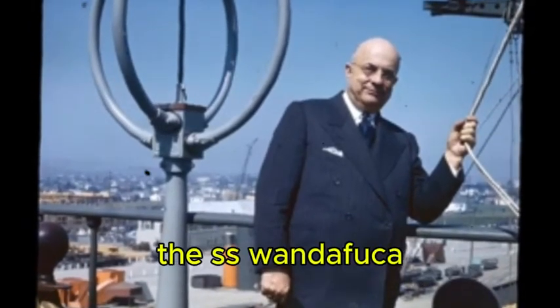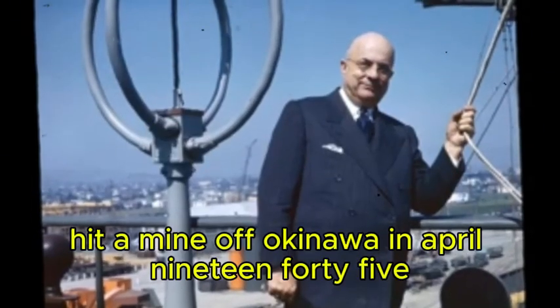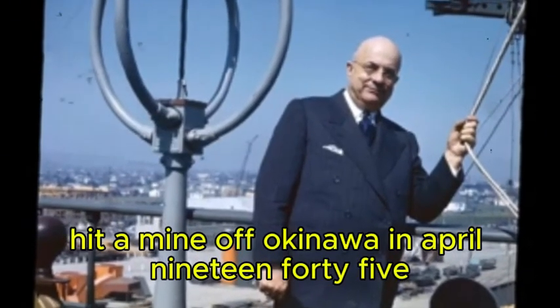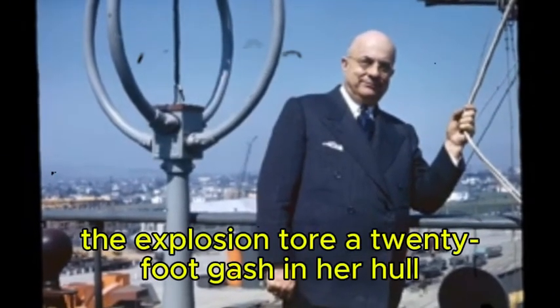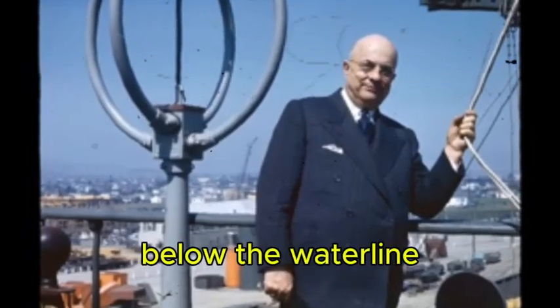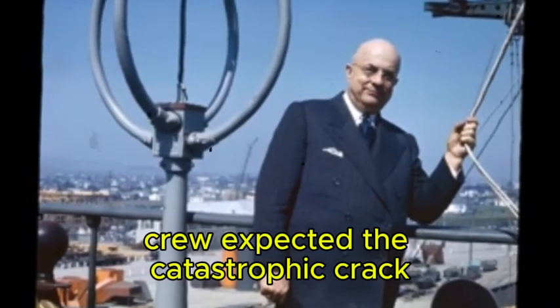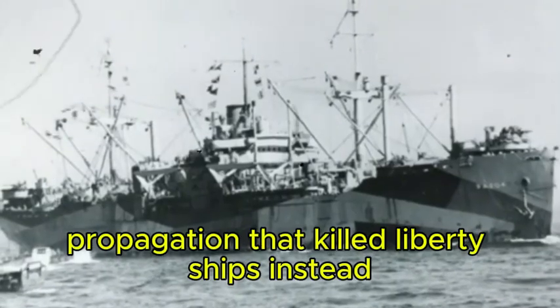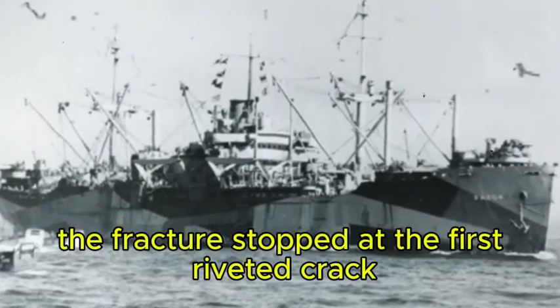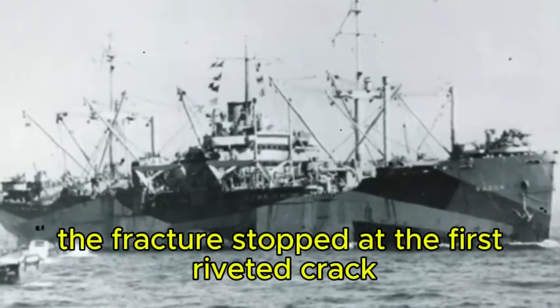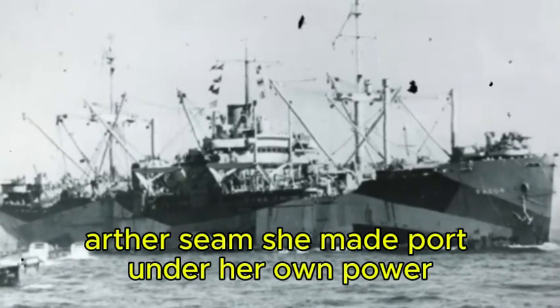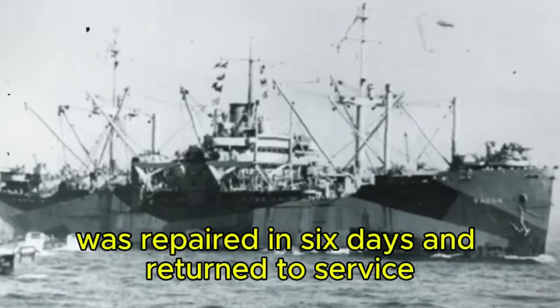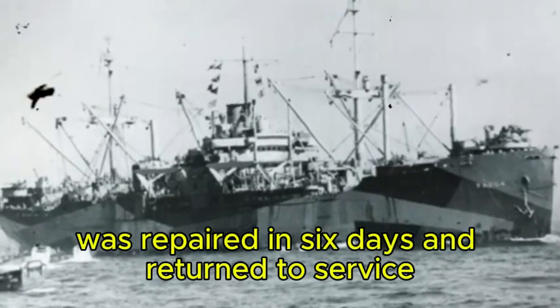The SS Juan de Fuca, a Victory ship, hit a mine off Okinawa in April 1945. The explosion tore a 20ft gash in her hull below the waterline. Crew expected the catastrophic crack propagation that killed Liberty ships. Instead, the fracture stopped at the first riveted crack arrester seam. She made port under her own power, was repaired in 6 days, and returned to service.